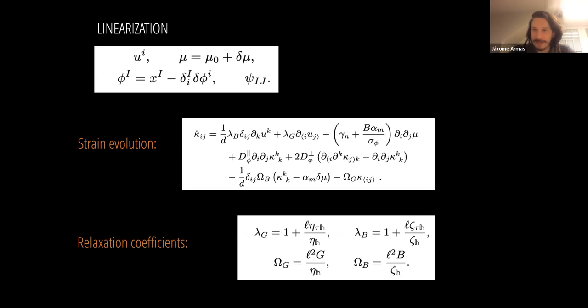Now, what plasticity does is affect the strain evolution. So if you now ask what is the time evolution of the strain, you get various terms on this right-hand side. These terms here, lambda_B and lambda_G, are there no matter what. And in this specific case, you can actually show that you can redefine the fields in such a way that these coefficients can be set to one. So they're not very important in this case. You see that the Goldstone diffusion coefficients affect this strain evolution equation in the usual way.